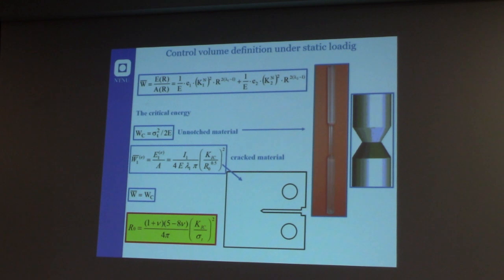So for defining the control radius under static loading, you need two fundamental parameters. You need the energy of the material for the unnotched material, and you need the energy of the material for the cracked material. So you need the test from the unnotched specimen and the test for the cracked specimen. If we consider the energy as the critical parameter for the material, we have to consider that the energy for failing the unnotched material is the same energy that we use for failing a cracked material. If you equate these two equations, it's possible to obtain R0, which is a function of the Poisson's ratio, of the fracture toughness, and of the ultimate strength of the material. So actually, it is a very simple closed-form expression that gives you R0, a material property, as a function of some simple tests that you can easily make on standard materials and also complex materials.